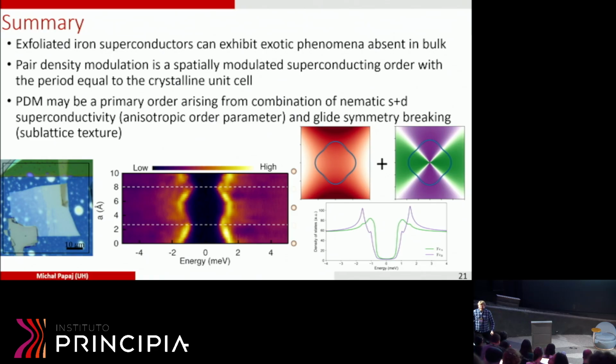I know, but you see the secondary gap in the density of states there, right? In your purple curve. Yep. Has this been seen in any of the data? Any shoulder? Unfortunately, it's too broadened. This broadening is not due to finite temperature broadening or anything like that. It's just that different states feel a different gap in the anisotropic system.